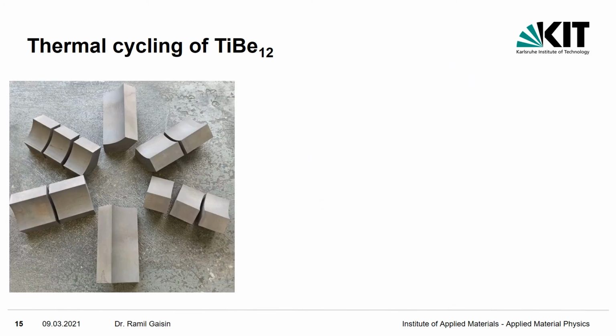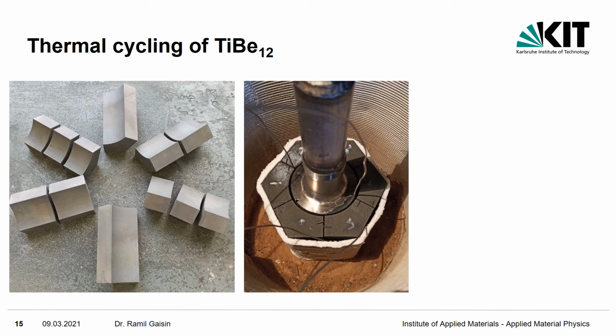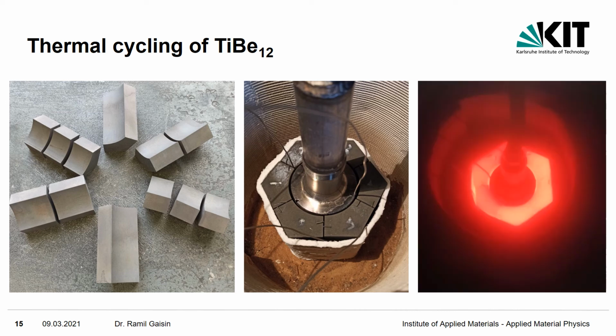During the operation in a fusion reactor, the beryllide will experience pulses of rapid heating and cooling. To simulate this, the beryllide block was split into several pieces to form several current circuits for rapid induction heating. A water-cooled steel pressure tube was installed in the center hole for rapid cooling, and this picture shows how it looks during the thermal cycling in a chamber of the induction furnace.